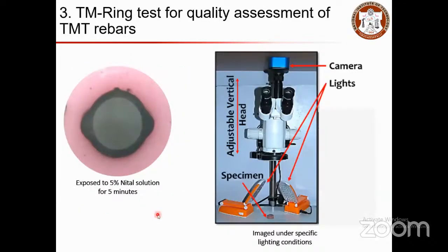So now what is the TM ring test? For doing the TM ring test, you cut the rebar and place it in this form. You prepare the surface, you cut it and you polish it, and that will be exposed to 5% nital solution for 5 minutes. Once you do that, you can see the phase distinguishing between the outer TM ring and the inner FP phase. To be more clear, you can keep this prepared specimen under this testing setup. You can see the arrangements for looking at the details of your specimens.